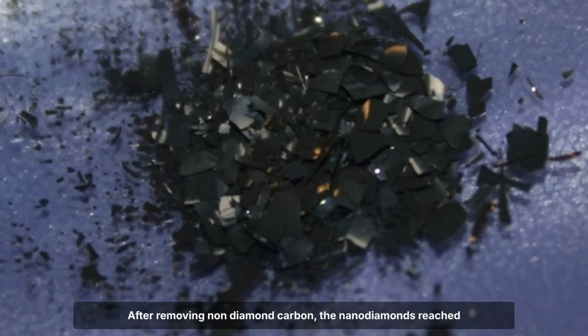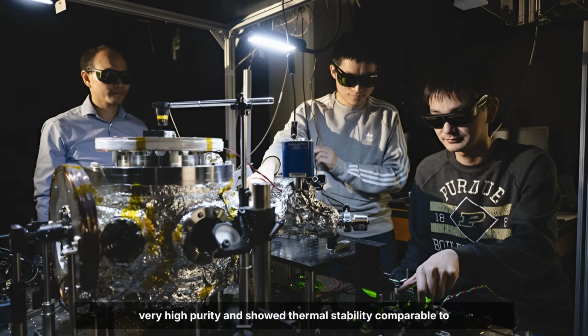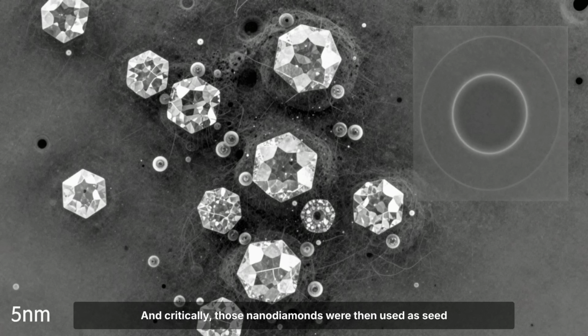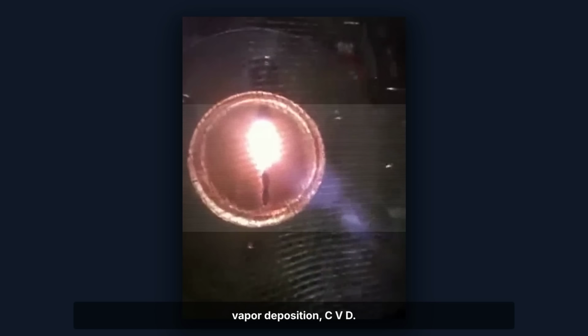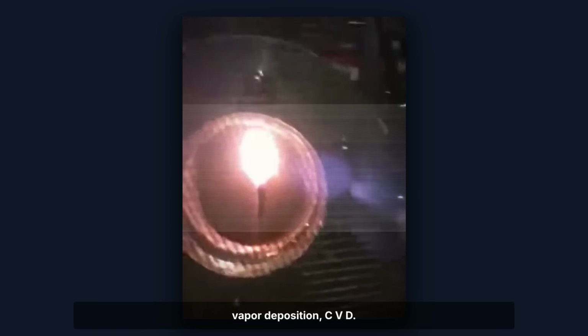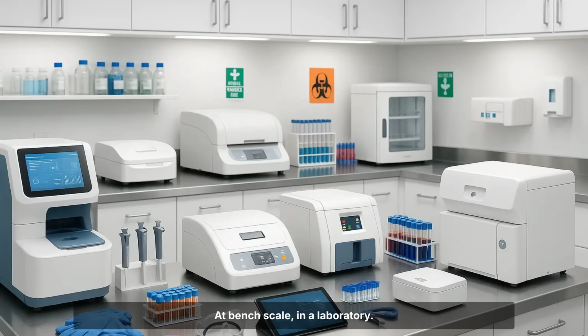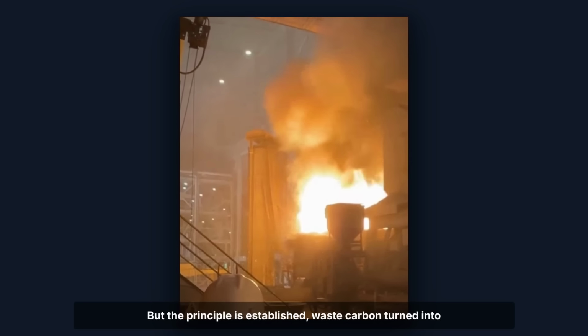After removing non-diamond carbon, the nanodiamonds reached very high purity and showed thermal stability comparable to commercially produced nanodiamonds made by conventional methods. And, critically, those nanodiamonds were then used as seed crystals to grow higher quality diamond films via chemical vapor deposition, CVD, at bench scale, in a laboratory, but the principle is established.